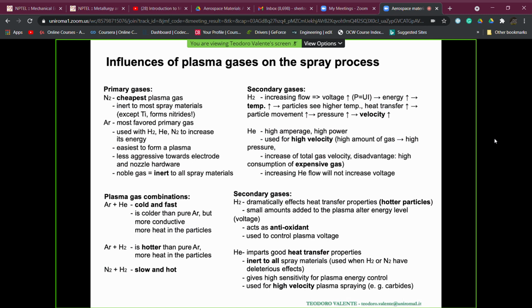That means if we want to fabricate a titanium-based coating, the use of nitrogen is not suitable, because we are going to incorporate inside the coatings nitrides, which are different in terms of composition, mechanical properties, and chemical physical properties with respect to the starting titanium. But this opens another window. This is one example